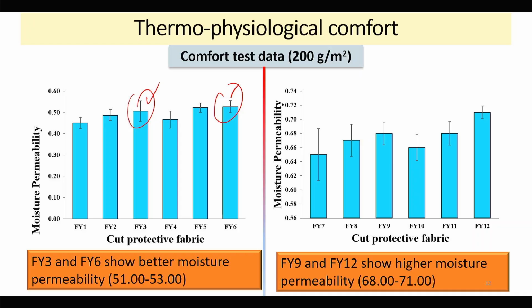And here cut protective performance is also high, because of the coarser thread, coarser core. So, the basic conclusion we can make is that we have to use a little bit coarser core filament, stainless steel or glass filament, which improves the cut protective performance along with the thermophysiological comfort, like moisture permeability, air permeability, thermal conductivity. So, at this point we will end the section of cut protective textiles.